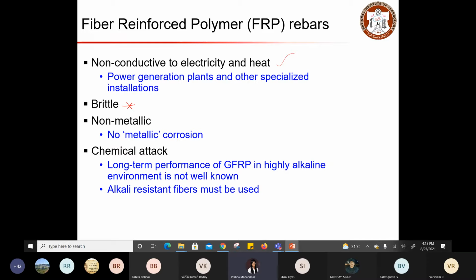But if you generalize the corrosion term as the cross-sectional loss or reduction in area, then you have to look at the other issue, which is chemical attack. When you generalize the corrosion term as cross-sectional loss, then you may observe such cross-sectional loss in FRP rebars also, though they are non-metallic. Why so? When exposed to an environment like a highly alkaline environment, since these are polymer based, they tend to degrade. When the polymer based rebars degrade, you will see a reduction in their area.